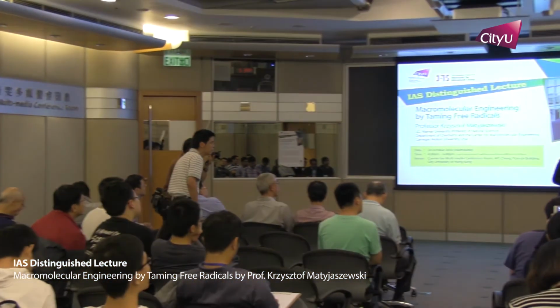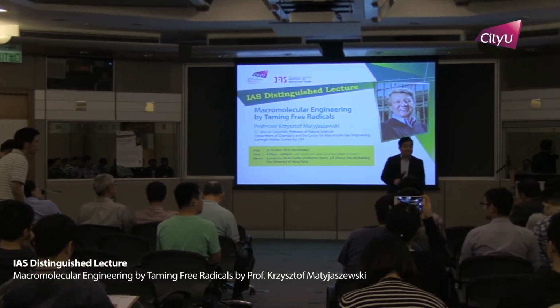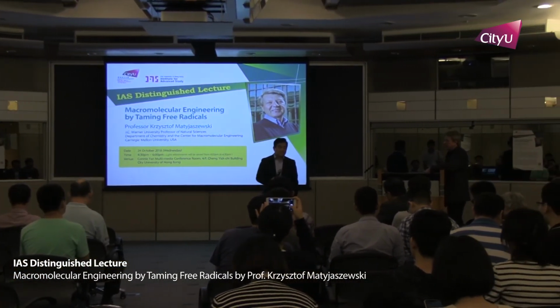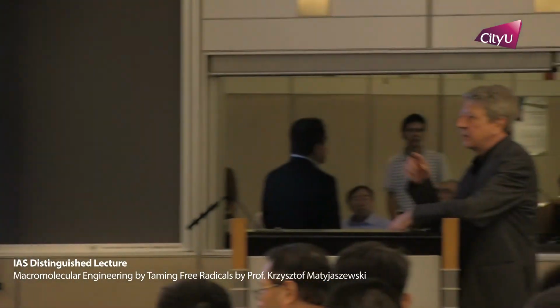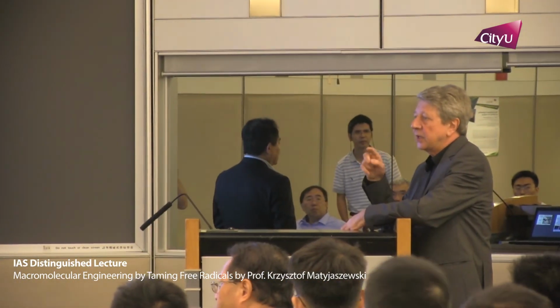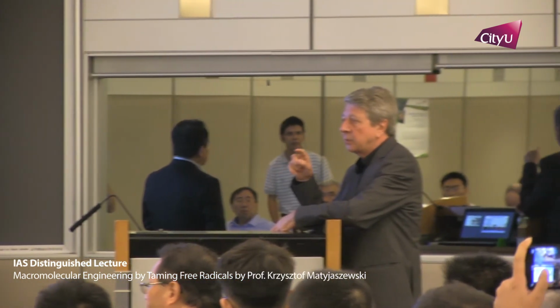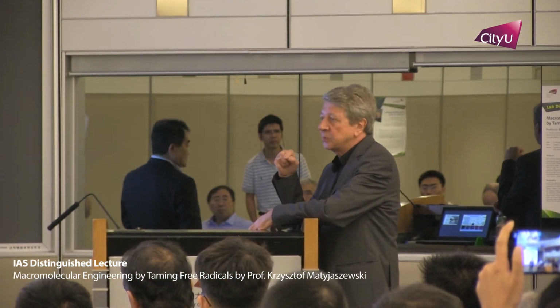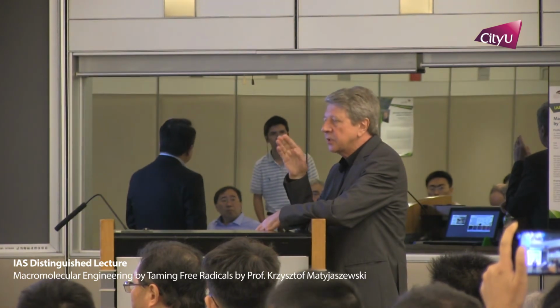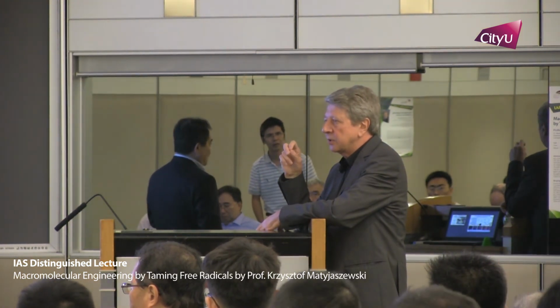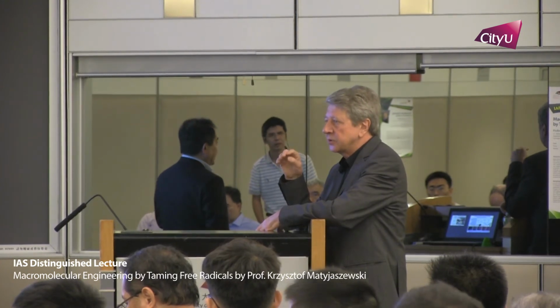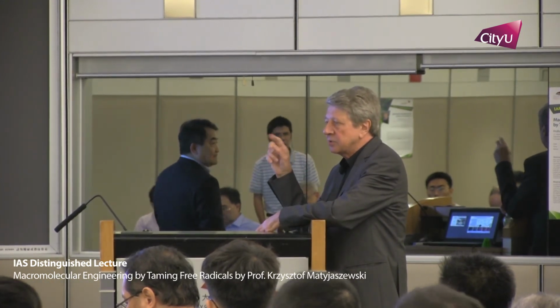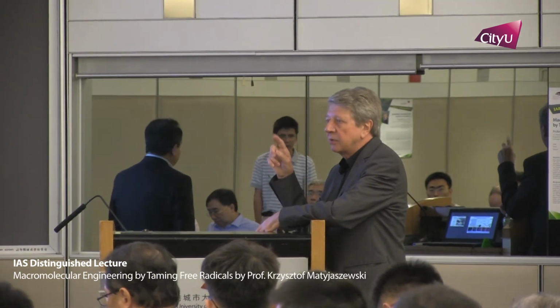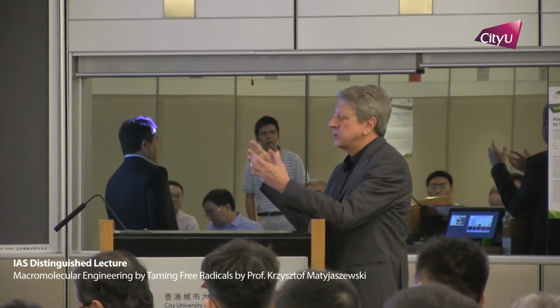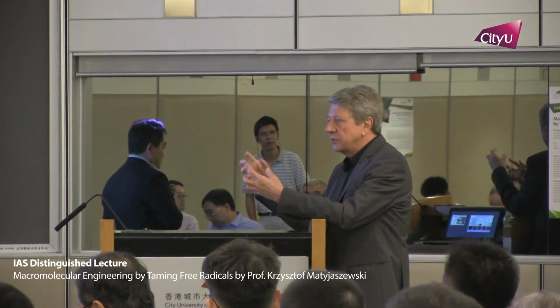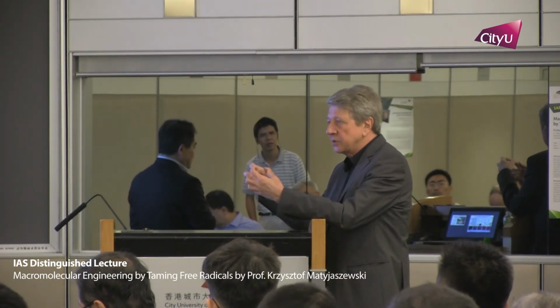Yes, so in fact, the largest piezoelectric effect is for barium titanate. And in that case, it can really provide electrons on the surface. And this electron can be transferred to copper-2 to reduce copper-2 to copper-1 species. But this is not only potential itself, but also affinity of the catalyst to a surface. So, for example, zinc oxide has much lower piezoelectric effect, but better performance. And in that case, it may be specific interactions of this copper catalyst with the surface as well.